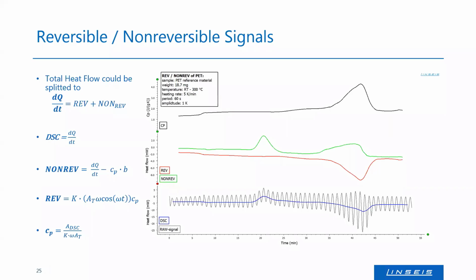And what we can also see in the range of the glass transition at around 8 or 9 minutes is a small endothermic peak in the non-reversing part. And this is this hysteresis peak I was talking about. So by splitting the DSC signal, we can see this hysteresis peak without the glass transition, and the glass transition without this hysteresis peak, because this peak is non-reversible, so it wouldn't occur again under normal conditions. Of course, if you quench the sample or something like this, it's possible to receive this again, but the character of this small endothermic peak is non-reversible. And at the bottom, you can see the total heat flow, the raw signal of this measurement.